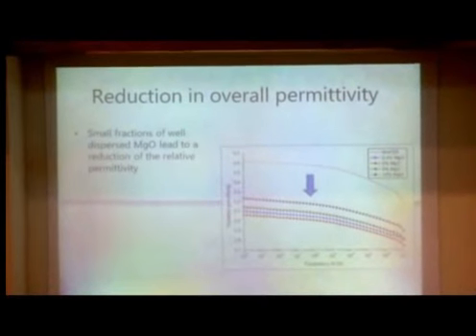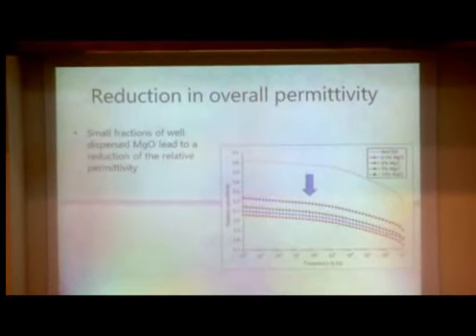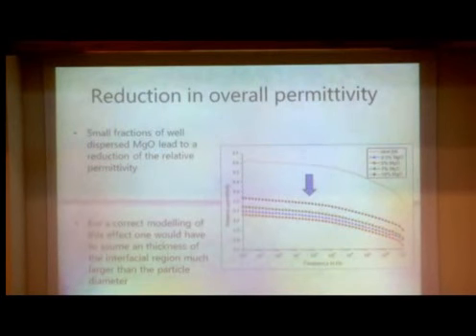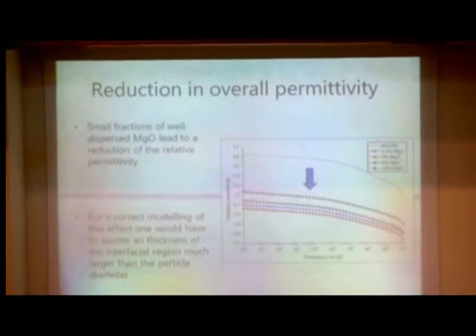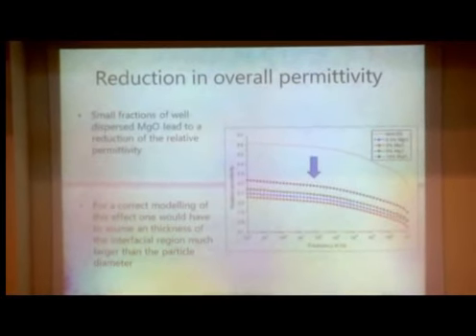And people started to model this behavior by assuming that the third medium, the interfacial zone, has a strongly reduced permittivity. Yeah? So you have then a three-phase system which would result in these drastic reductions of permittivity, up to 20%, which is quite a lot. However, for correct modeling, assuming that this is the working principle, we would have to assume an interaction of the nanoparticle with the surrounding areas that extends way beyond what we think is possible. So here again we are at a loss.